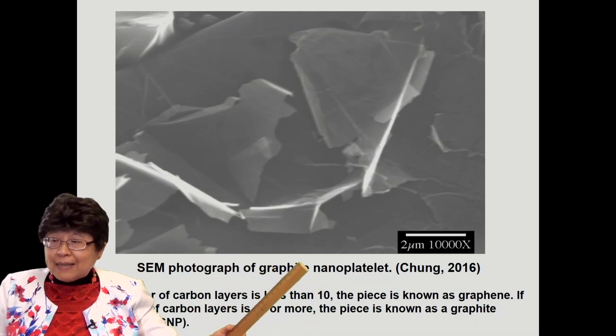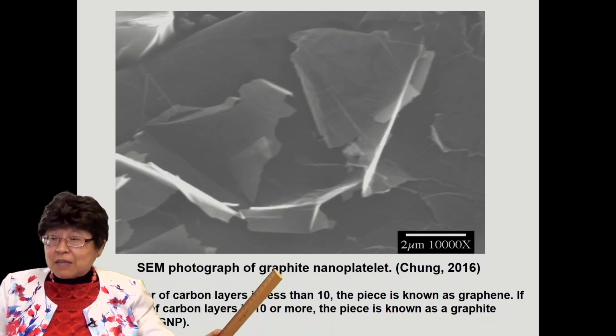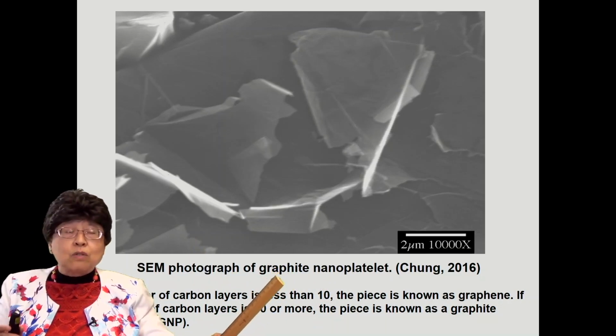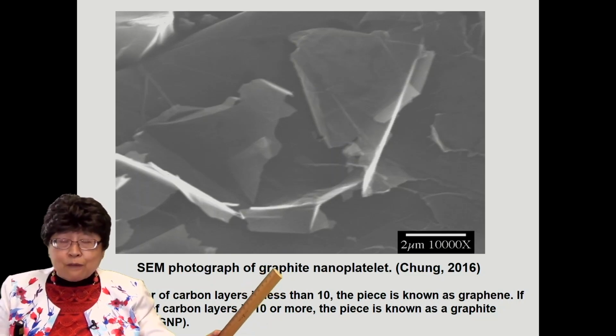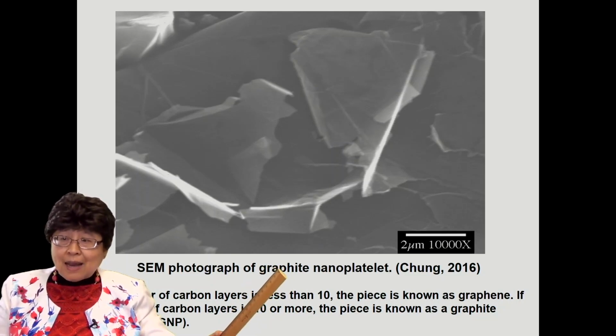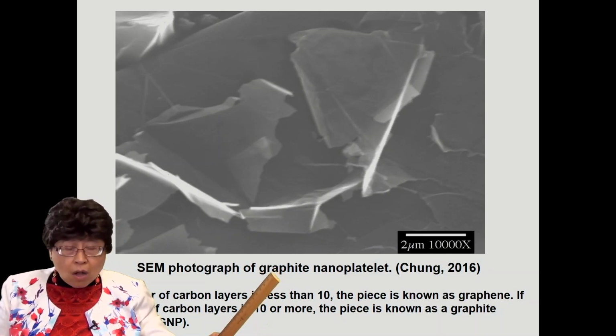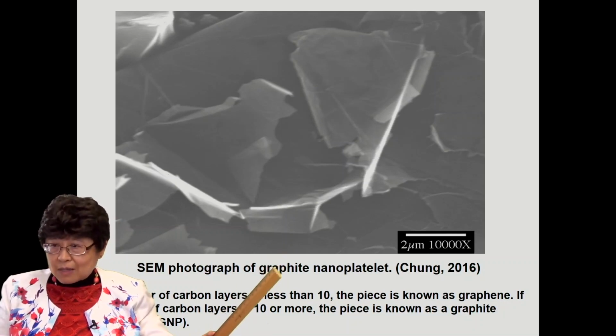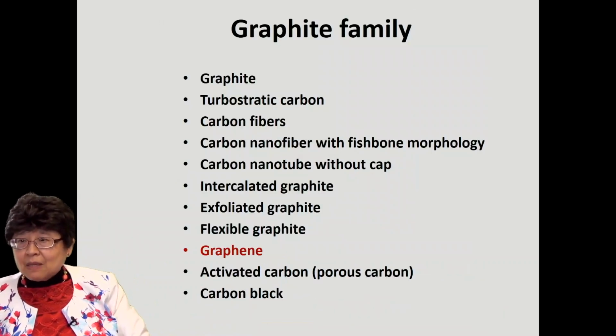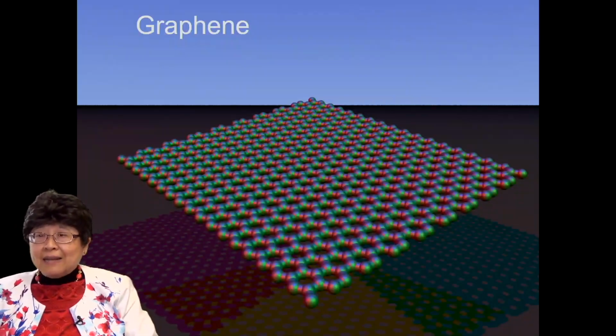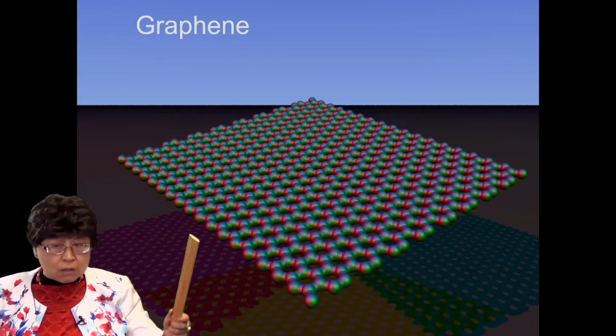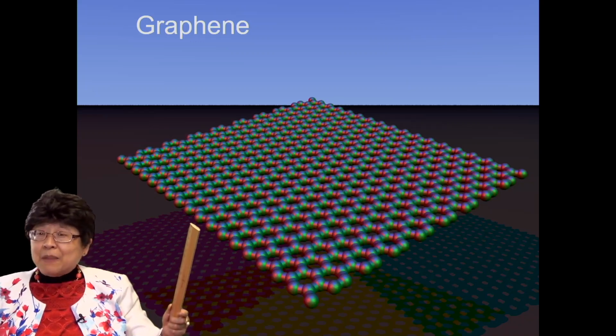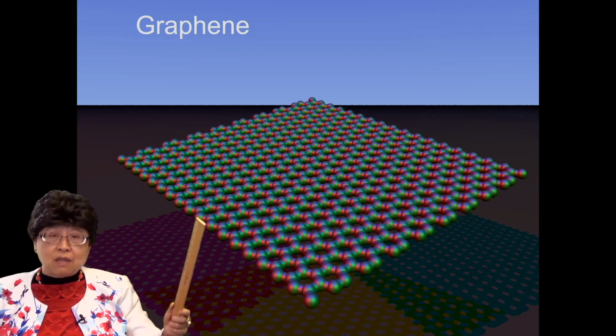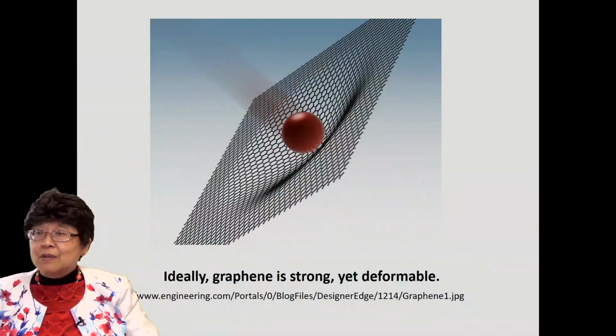But we call it graphite nanoplatelet, not graphene, because one should use the term graphene only if the number of layers in the stack is less than 10. Okay? If it's greater than 10, one should not call it graphene, but call it graphite nanoplatelet. Graphene, ideally, is a single layer. That's the original definition of graphene. However, nowadays people have loosened that definition to include up to 10 layers.